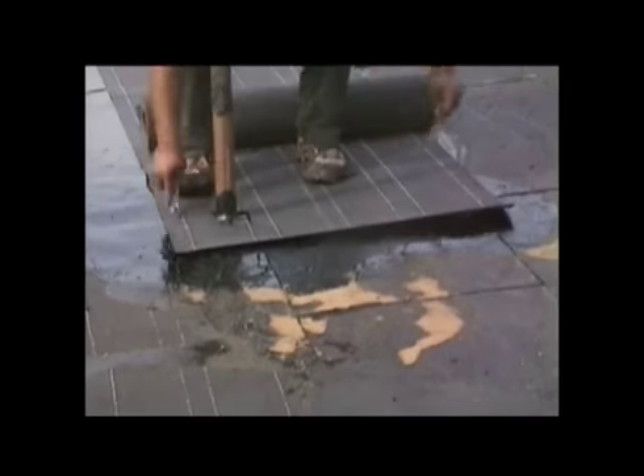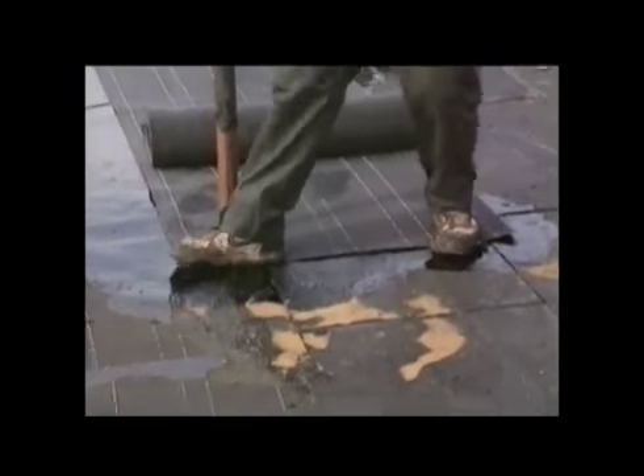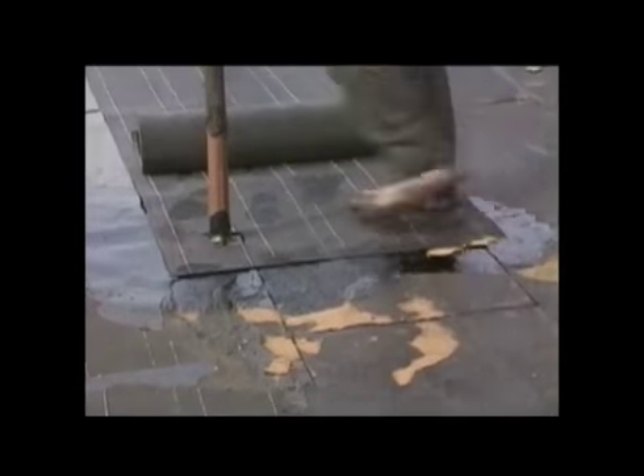A simple void the size of a quarter can cause a blister several feet in diameter. 75-pound rolls are hard enough to work with, no less having to perfectly glue them together with a 2,000-degree torch or 500-degree asphalt. Both can't be touched, stick like flypaper, and are too cold to adhere properly in less than 10 seconds. At completion, you have 3/4 of a mile of exposed seams for every 100 squares, or in the case of single ply, fewer exposed seams, but a fragile system with no redundancy to stop anything if there's even a minute imperfection in the material or the seam.